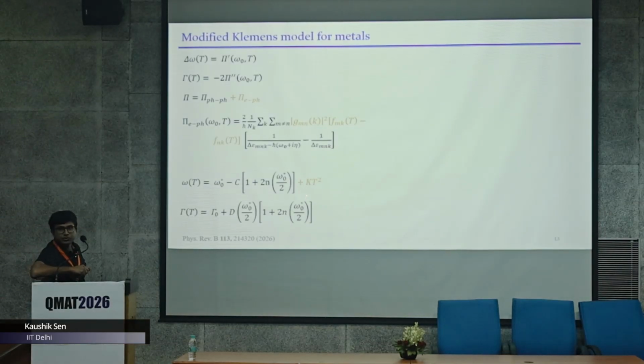Now, if you use this self energy, what we got in the frequency expression, there is an extra term coming, kT square. Okay. You might say that in the Fermi liquid there is a T square term, right? In the magnetization data there is a T square term. Now phonon also has a T square term. This is the pure result of the Fermi-Dirac distribution function, nothing else. It's like a phase space scattering thing.